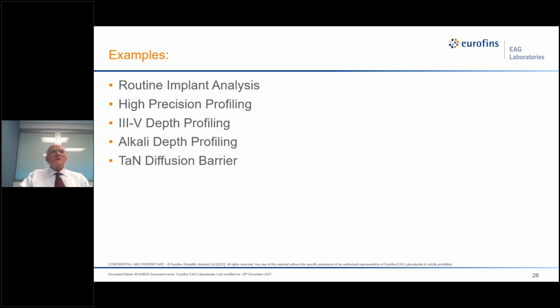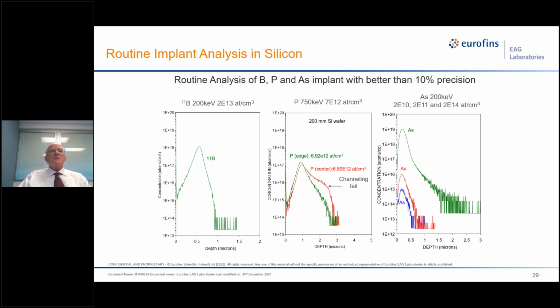So I have some analyses here, examples, and all of these pertain to the questions that you guys have asked. Here is an analysis of simple boron implant into silicon, and I show this to show detection limits. People say, well, what kind of detection limits can I get? Well, these two are 5e13 per square centimeter. Silicon is 5e16 per square centimeter. So this is 1 part per million atomic. 1, 2, 3, this is 1 part per billion atomic. And down here, we're an order of magnitude less, and that's 1/10 of a part per billion atomic.